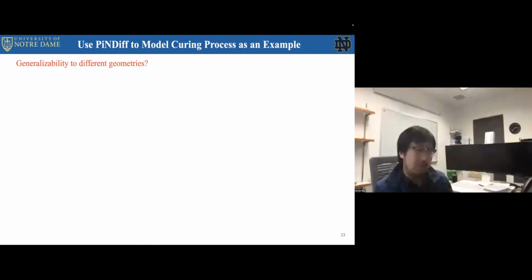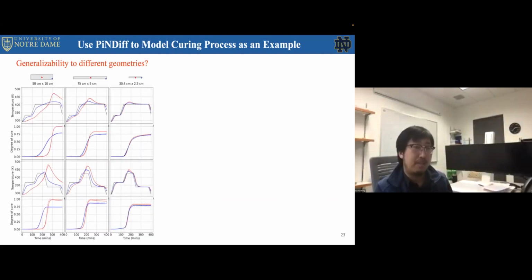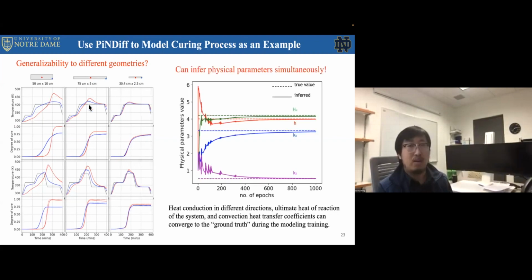The good thing about this is that because we're trying to learn the operator, it is mesh invariant or discretization invariant. So it can be generalized to different geometries. If our sample is not a square domain and becomes rectangular, with different aspect ratios, it still can work. And also, like I mentioned, during this training process, there are some unknown physical parameters, and we can infer those physical parameters. You can just make those physical parameters trainable, the same as the neural network parameters. You can see during this process that those physical parameters converge to the ground truth, which is the red dashed line, given a sufficient number of training epochs. So the heat conduction, the ultimate heat of reaction of the system, and the convection heat transfer coefficient can converge to the ground truth during this model training.